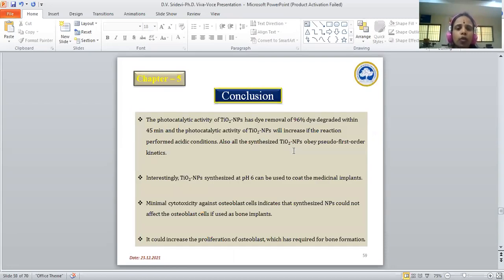Conclusion: the photocatalytic activity of TiO2 nanoparticles has dye removal of 96%, with the dye degraded within 45 minutes by using RB5 dye. And the photocatalytic activity of TiO2 nanoparticles will increase if the reaction is performed in acidic condition. Also, the synthesized TiO2 nanoparticles follow pseudo first order kinetics.